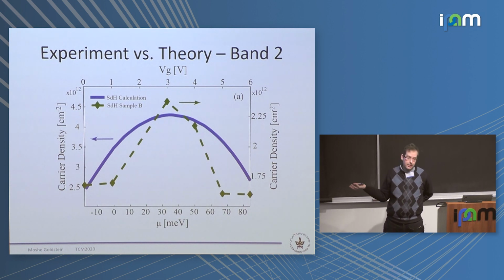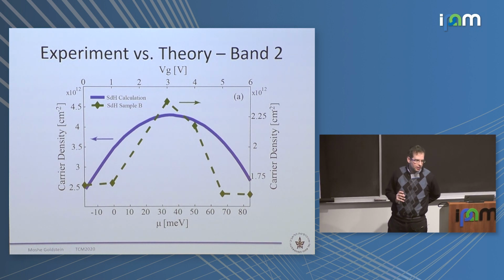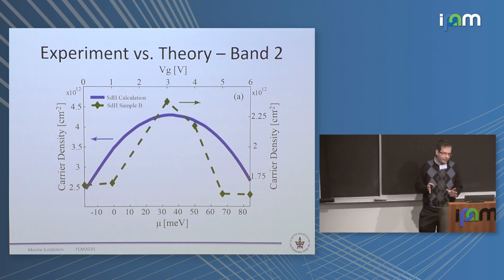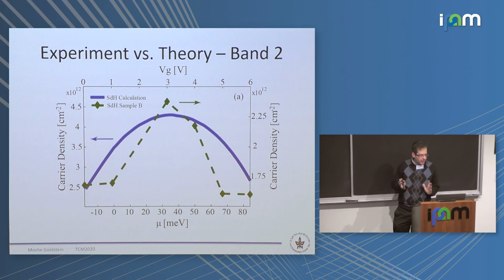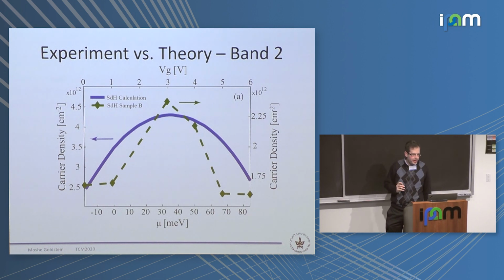So, they barely see Shubnikov. Basically our assumption is that band number 1 has a lower mobility, and then it's below what they can see, and band number 2 has higher mobility, and they see only that. In any case, they don't see 2 frequencies, although it's kind of clear that 2 bands are playing a role there. So they only see the more mobile band, and there are reasons to believe that this is the upper one, and it definitely gives a consistent picture.